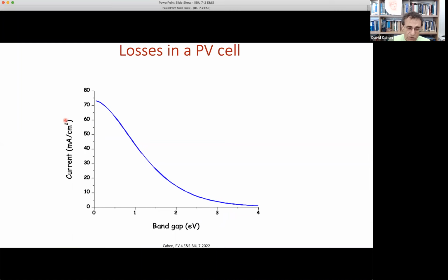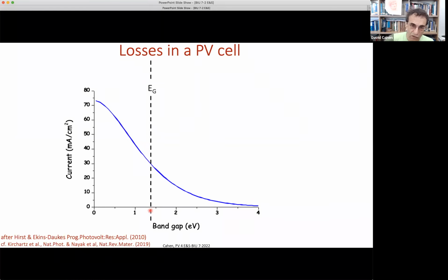And this is the current when I am putting the cell on short circuit, and it's ideal. So I am assuming every photon that is absorbed by the system gives me an electron that can flow in the circuit. And so you would get, at nearly zero band gap, theoretically, over 70 milliamps per square centimeter. And this is naturally taken according to the solar spectrum, AM, air mass 1.5 global, for those who know what that means. Let's take a system where this is the threshold of absorption, the band gap of my semiconductor that determines how this solar cell works.